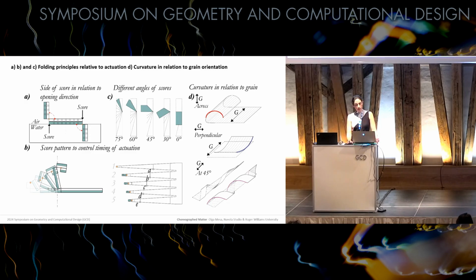The structural composition of the paper used was unidirectional, enabling it to expand, fold, and bend easily across its grain and less easily perpendicular to its grain, shown in these diagrams and their cross-sections. To determine the different flexing actions relative to fiber orientation, a paper test with radial designs was placed in water, and the water was absorbed.